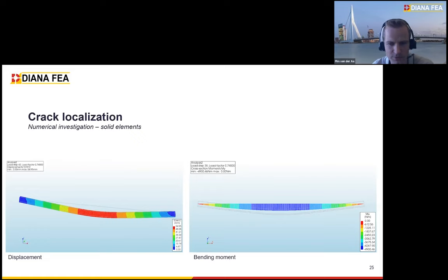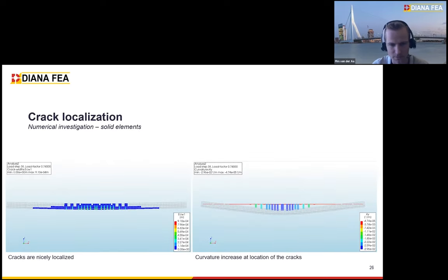In the next slides, we're investigating the solid model. What is good to see is that in the right image, you see the exact same bending shape as was expected, since it's a statically determined structure. However, where we now look at the cracks, you can see that the cracks are now nicely localized, which would also mean that the strains are nicely localized automatically, because they're related by the crack bandwidth. And on the right side, you can actually see that at these locations of the cracks, the curvature is increased significantly. And between the cracks, you can see that the curvature is relatively low.